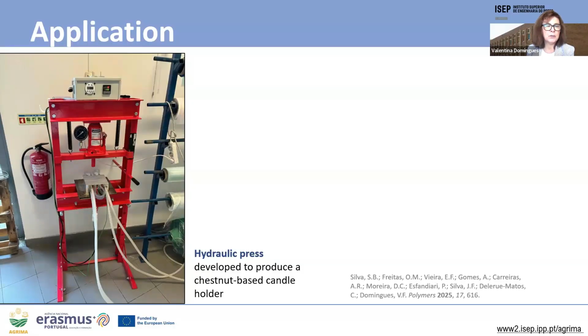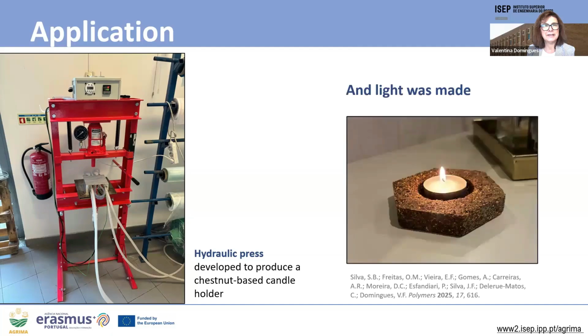After all tests were performed, we developed a hydraulic press to produce a candle holder, and a light was made, as you can see. We produce this candle holder using a composite with 75% chestnut, treated with shellac and processed at 120 degrees, and the glycerol was excluded. This pioneer prototype illustrates the practical application of these research findings, showcasing how chestnut waste can be transformed into a functional product, emphasizing sustainable practice in waste valorization.